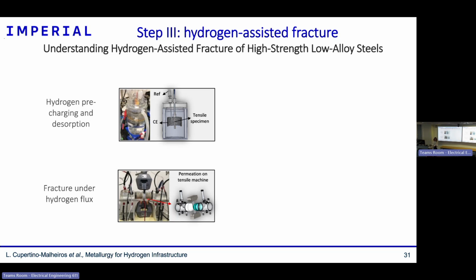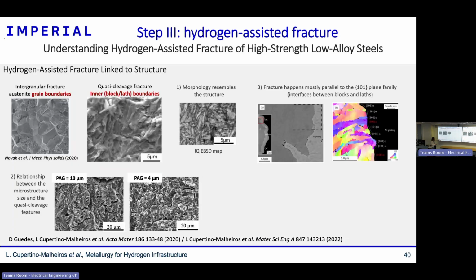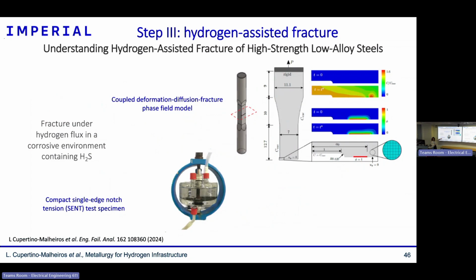Yeah. Actually, would it be possible to take this kind of accumulation, where you get more and more hydrogen into the material, into account in your modeling? Yeah, it does. Here it is quite static modeling, but this type of modeling here does take it into account. It's a diffusion fracture phase field model. So when the crack is evolving, it's already taking into account the change in the stress field, and you also solve the diffusion of hydrogen, and that's good because then you can capture the kinetics. In those cases, you have in situ experiments. There are lots of kinetics involved: the kinetics of how fast hydrogen moves, and the kinetics of your crack propagating, and those are related to each other. So those types of models can capture all of this.